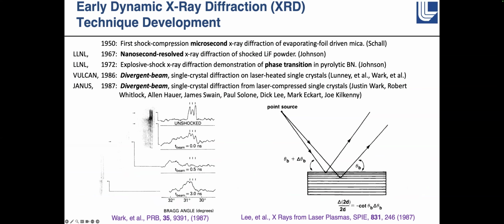But not much was done with it, partly because the data is not very good. And it was 17 years until Quentin Johnson at Livermore demonstrated that he could do nanosecond resolved diffraction. The first shock experiments were microsecond X-ray sources. Johnson developed a nanosecond source and measured much more rapidly. He demonstrated that you could measure a phase transition by diffraction in a shock compression in 1972.